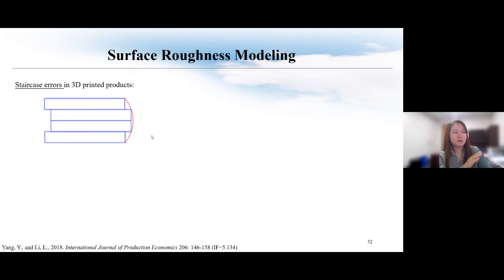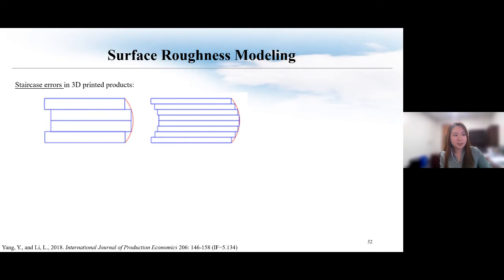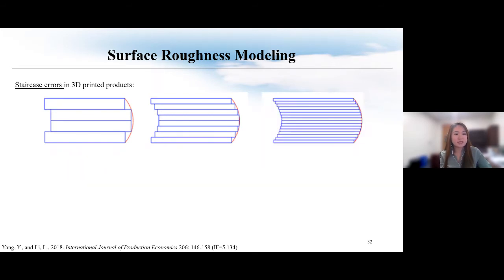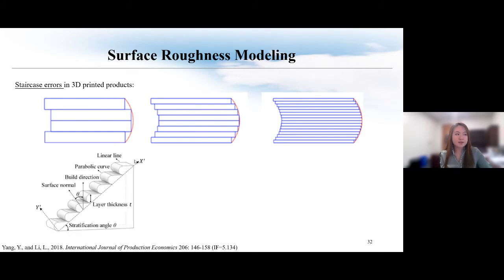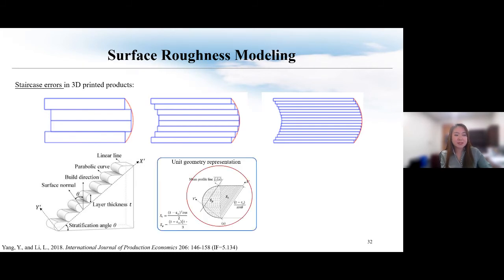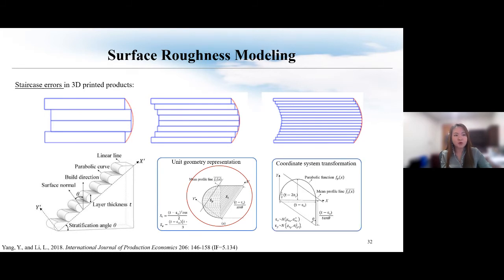You can see if you print this part with 4 layers, there are a lot of voids here, and that's a significant defect. Now, if you increase the number of layers, that defect becomes less significant, but you can still see the staircase errors. Now, if you further increase the number of layers, that defect becomes less significant, but if you use a microscope, you can still see those staircase errors. So what we did here is we use this surface profile to represent the actual staircase errors. And we were able to get the mathematical representation of this profile, and then we transform the coordinate system back to the actual surface, and we were able to build a model for calculating the surface roughness.